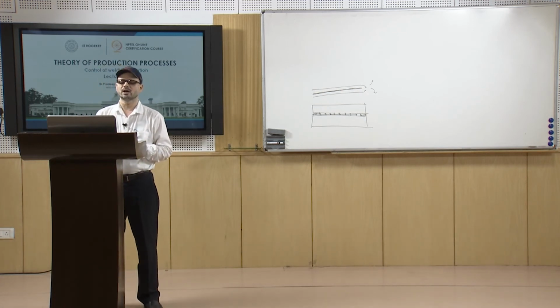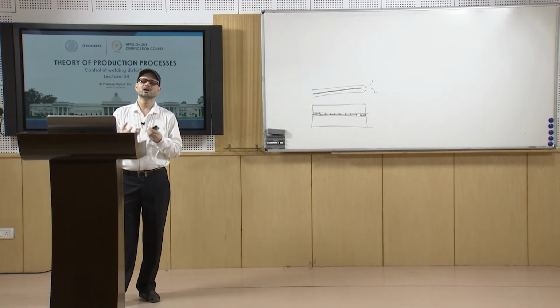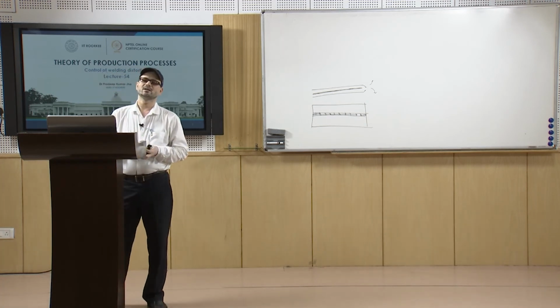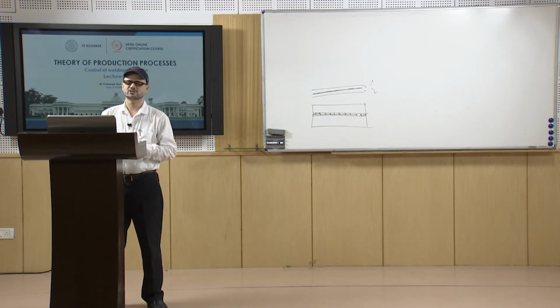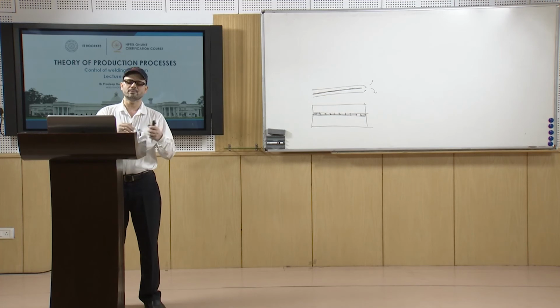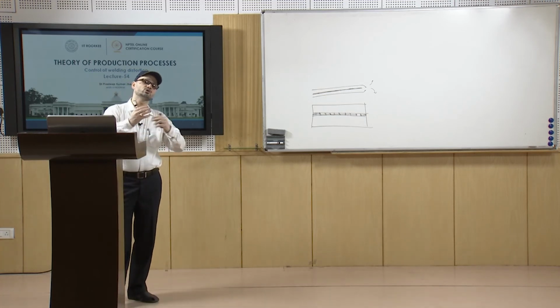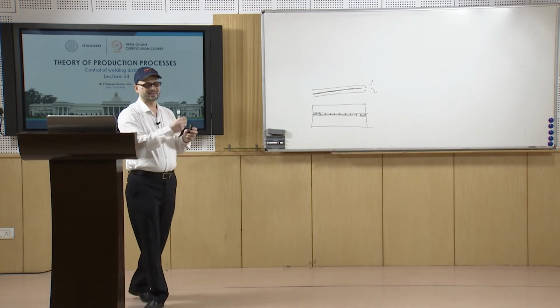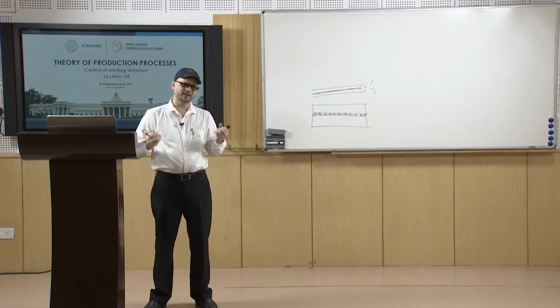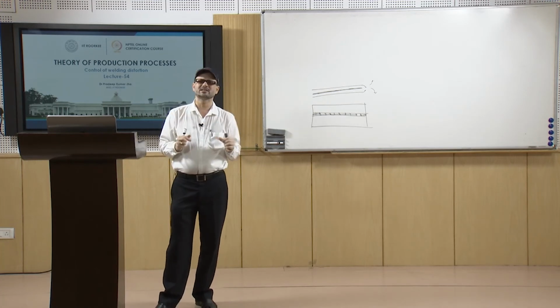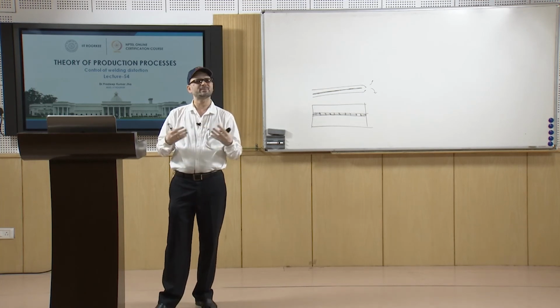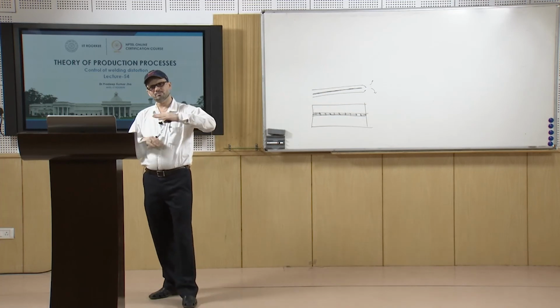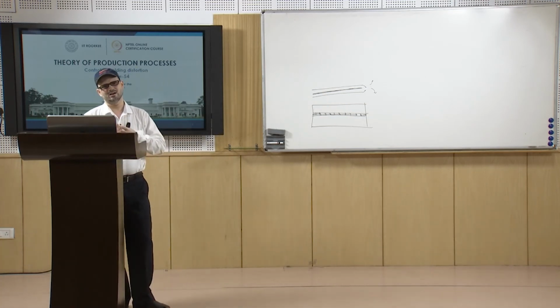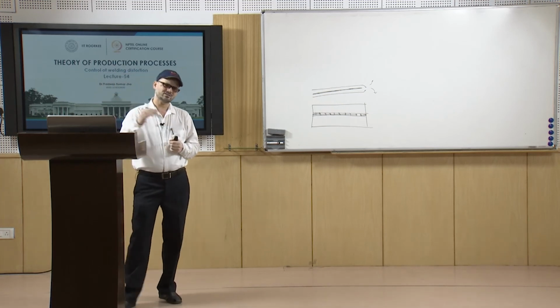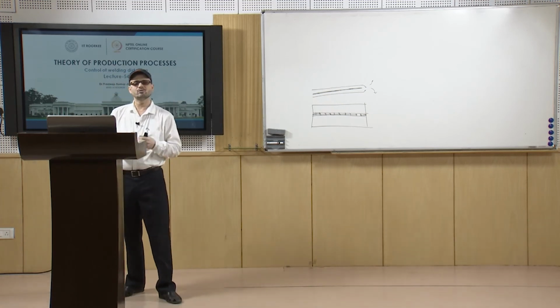And we can also use a water cooled jig many a times, because copper tubes are brazed to the copper holding chamber, and then water is circulated through these tubes, and most of the heat is taken away by this water. The purpose is that when you have a thin sheet, it is very difficult for it to carry that much heat in such a short time, and because of the heat it may buckle or distort. So, we place some conducting material that allows the extraction of heat quickly, and the distortion will be a minimum.